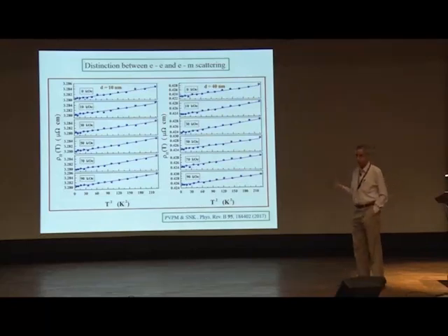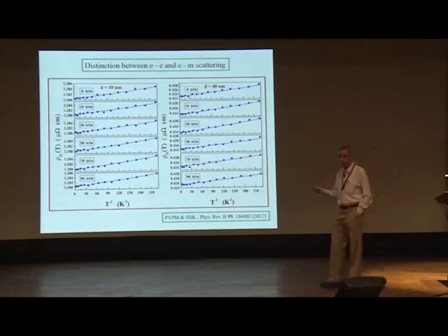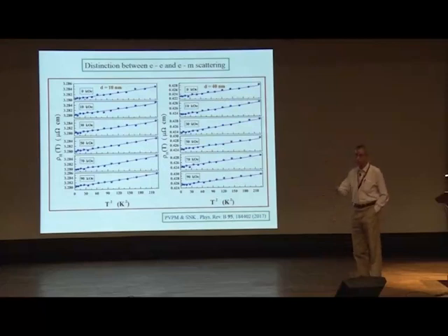And this was seen not only in iron, cobalt, nickel, but in numerous alloys, throughout all metallic ferromagnets of all kinds. They saw this T-square dependence and attributed it just to electron-magnon scattering. And we show that that is not true. One has to do this experiment to find out whether that is so or not.